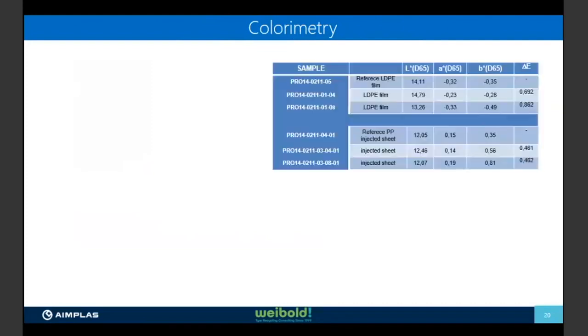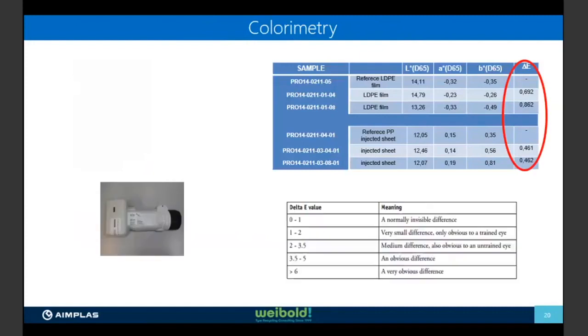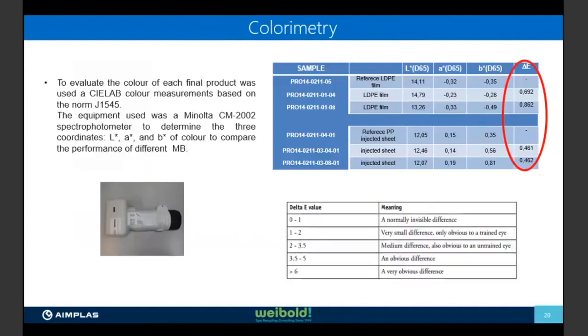And at the end, what we did, because I said, okay, they are very similar, so the properties would be more or less the same. We did colorimetry, to assess that we are having a good impression. When you do colorimetry, you measure the coordinates L, A, B, and to check how far you are from a color, you calculate delta E. And here in the right side, you can see that delta E is below 1. Normally, in the table down, you can see that depending on the value of delta E, you are going to have some deviation with the color.